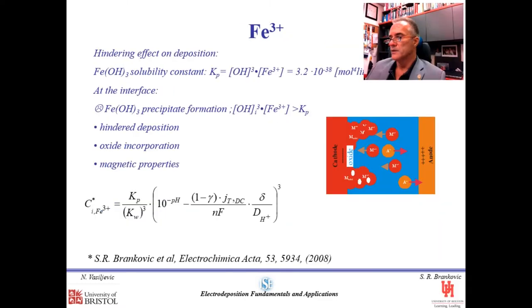More important, along the previous discussion and using the example of iron 3 plus, I would like to emphasize the very important fact that when we do have electrodeposition of metals which happen to have co-deposition of hydrogen involved in this process, then we have to appreciate the fact that the interfacial pH at the electrode surface is always very much higher than the bulk. In particular, iron 3 plus forms one of the most insoluble hydroxides, where the solubility product is very, very small. Therefore, understanding the situation at the interface is of great importance.